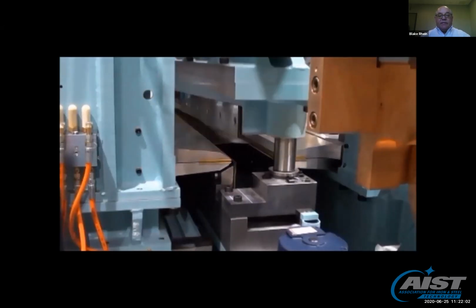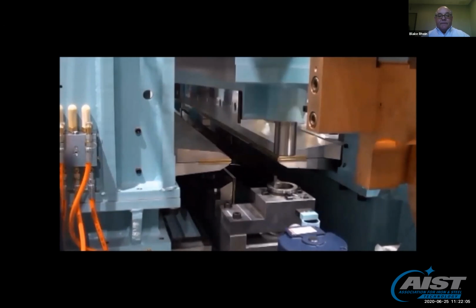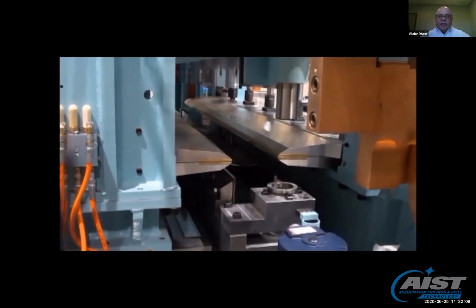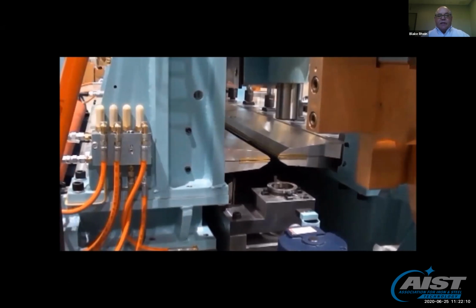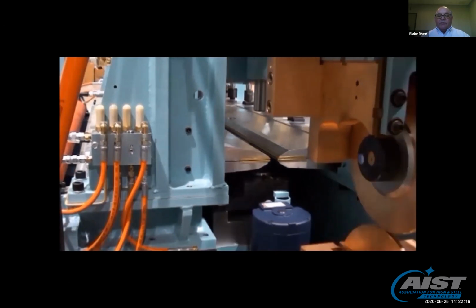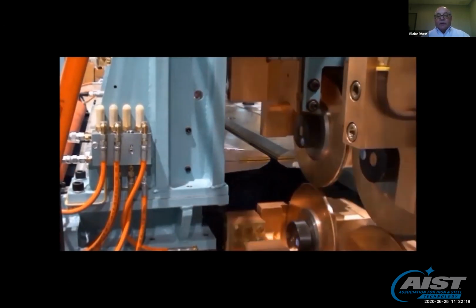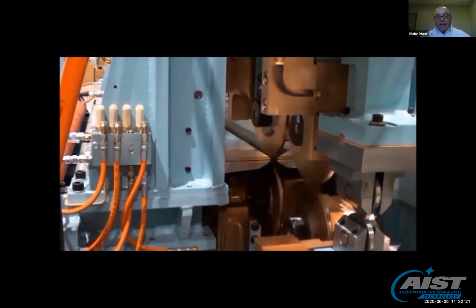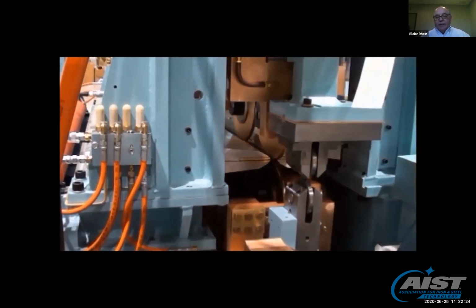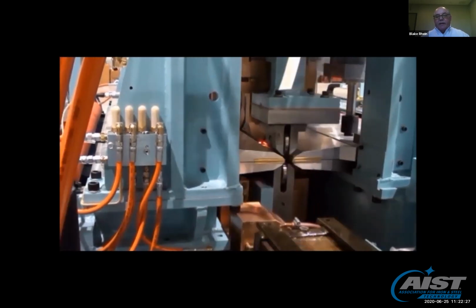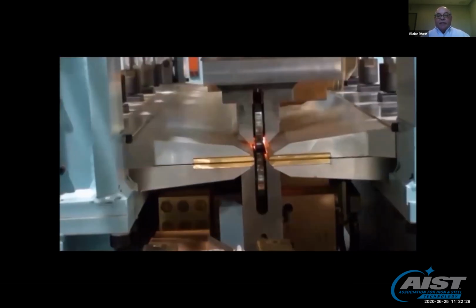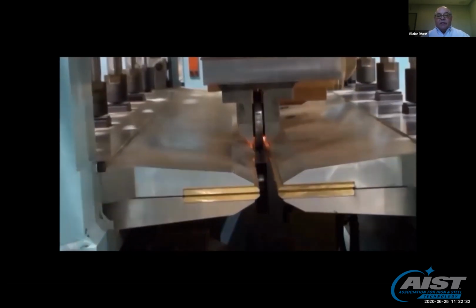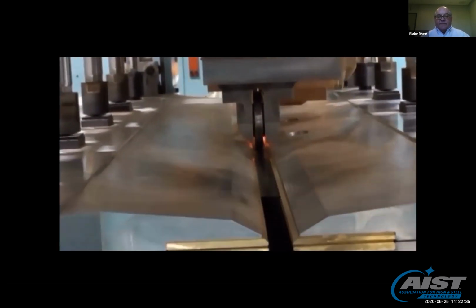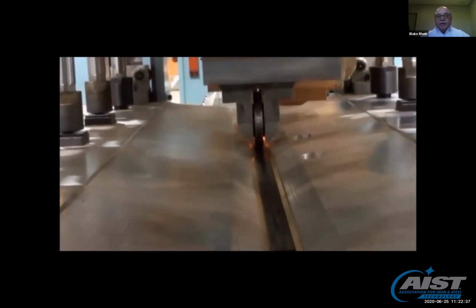Here is a typical machine cycle. The clamps are closed, the exit shears the material, the entry clamp moves in, the exit clamp pivots down, and then the welding carriage drives the welding wheels across the strip material. That happens to be two pairs of welding wheels. The small silver wheel following behind is called the planish wheel that simply polishes off the weld and makes sure there's little or no weld over thickness. So this is the sequence moving across the strip material, making the weld.